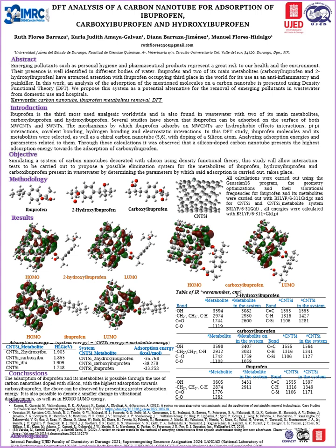On the other hand, the largest HOMO-LUMO energy difference corresponded to the nanotube ibuprofen structure at 1.909 electron volts. It is also possible to observe in the adsorption systems that ibuprofen is the molecule that has the smallest interaction surface with the nanotube, since it has relaxed perpendicularly with respect to the nanotube.